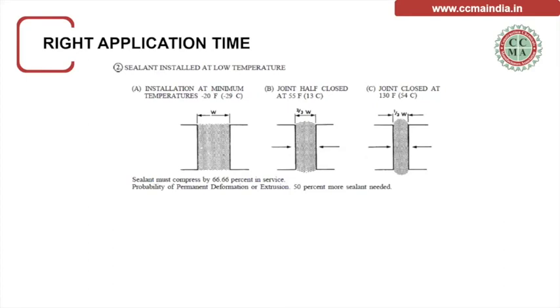Now, what is the right application time for the sealant? If you consider a hypothetical scenario, the sealant is applied at a temperature of minus 29 degrees Celsius and the sealant width is W. Now, when the temperature reaches 13 degrees Celsius, the gap has closed and the sealant width has reduced to 1/2. Further, when the temperature increases to 54 degrees Celsius, the width of the sealant is reduced to 1/3. So what you're finding is the sealant is getting compressed by 66%, and there is a high probability of permanent deformation.